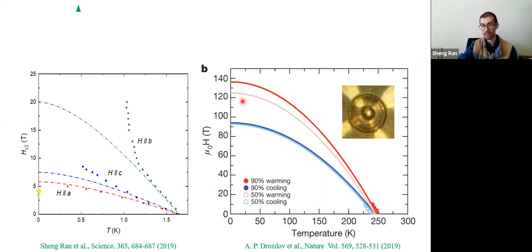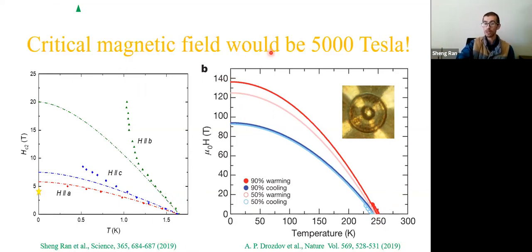last year people discovered room temperature superconductivity. This is lanthanum hydride under pressure, and the critical temperature is 250 K. That's room temperature at some places. So the critical temperature is that high, and the critical field is about 140 Tesla. Now here, our compound's critical temperature is only 1.5 K, but the critical field is 35 Tesla. If we would scale the critical temperature, then the critical field for uranium ditelluride would be 5,000 Tesla. This is incredibly high.